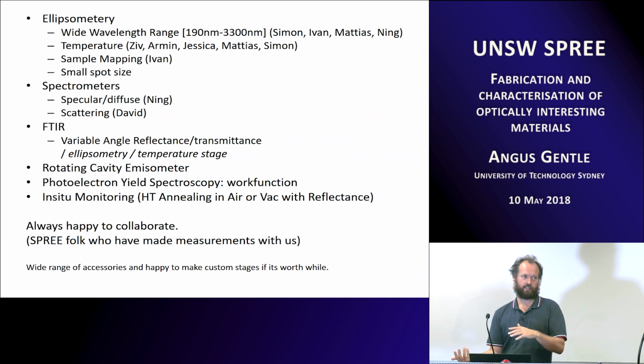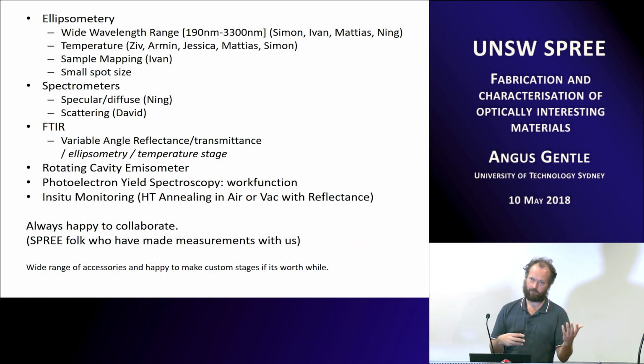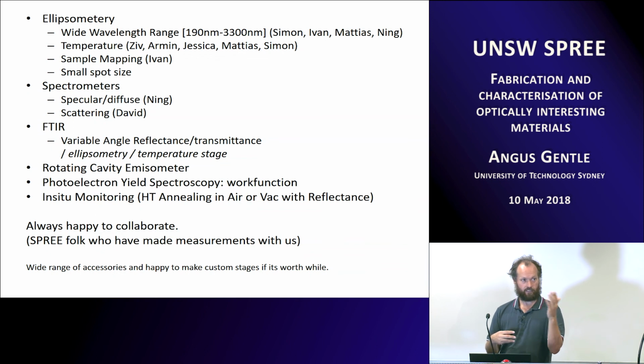And we've put temperature stages on this as well, basically because we also work on things like vanadium dioxide, which has a metal oxide transition from an insulator to a metal at around 68 degrees C. So we've got quite a few stages designed from room temperature to 100 degrees. So then we can measure that from UV out to 25 micron and get refractive index data across the whole thing. Rotating cavity emissometer, so if you just want to look at the emittance of a surface.